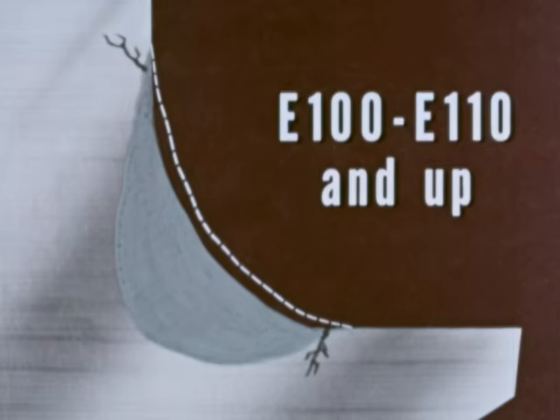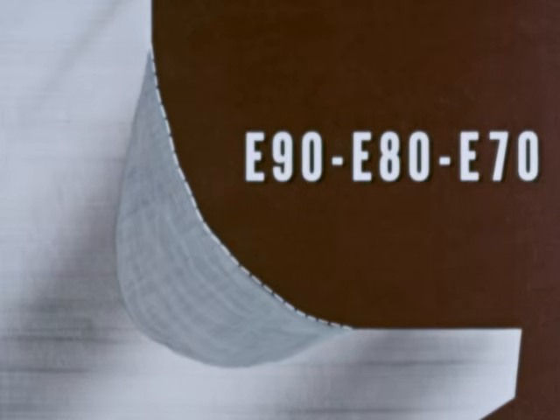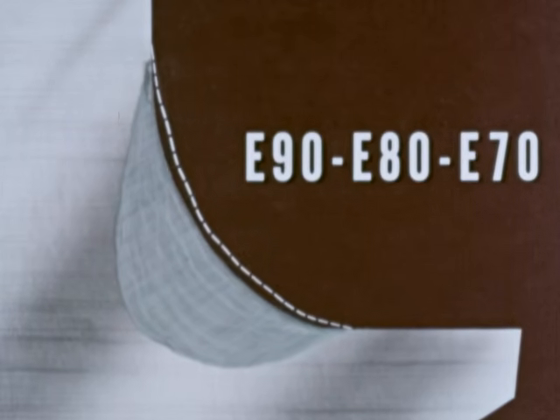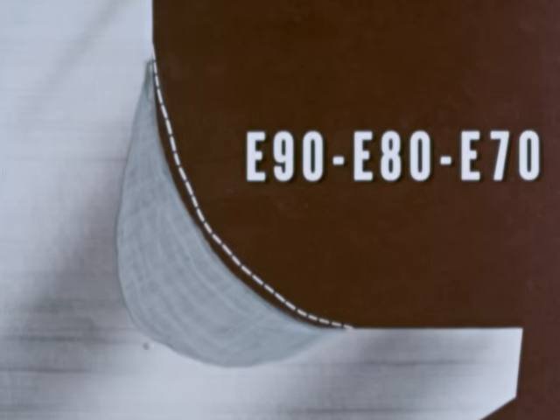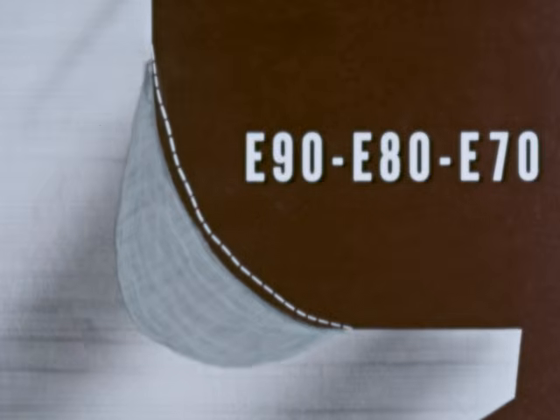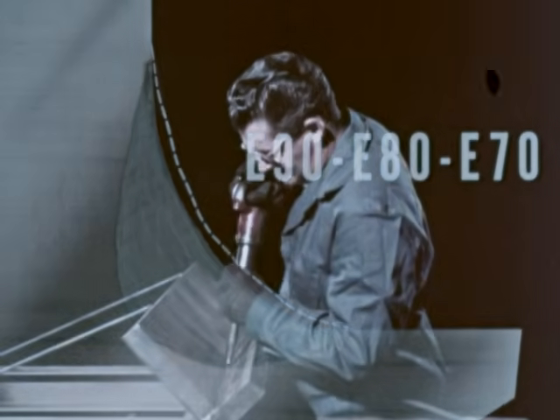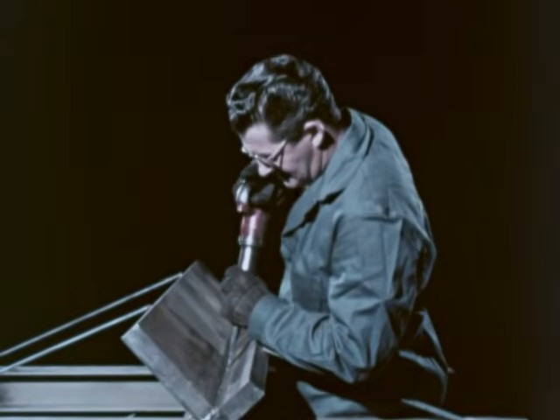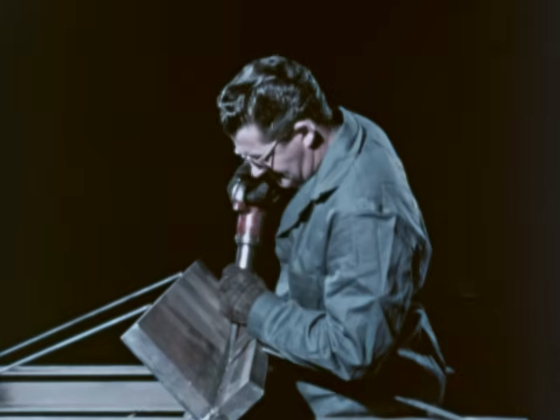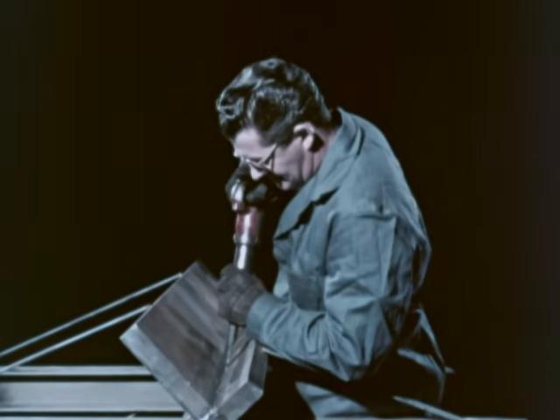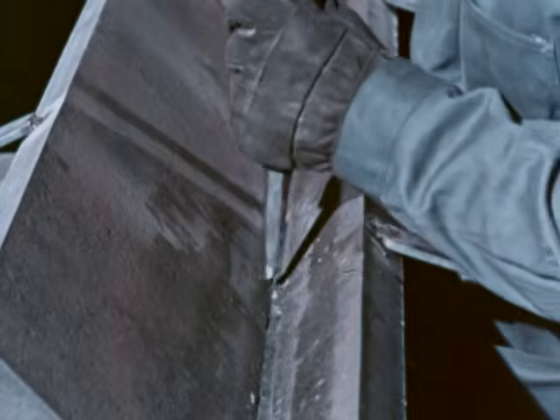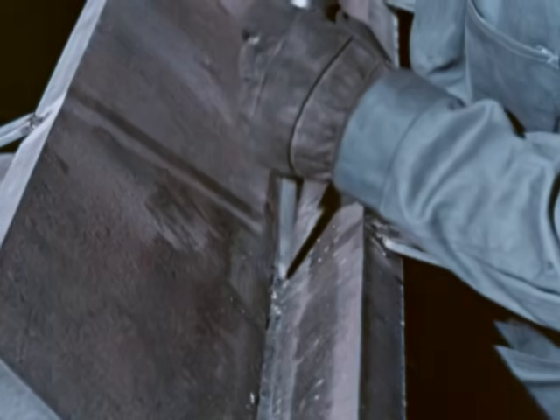One way to reduce restraint caused by shrinkage is to use more ductile rods. Rods lower in strength, since T-joints usually need less strength than butt joints. However, if the joint must have the higher strength rods, you can peen the weld, actually push the deposited weld metal around, thus reduce shrinkage forces and make a weld that is free of toe cracks.